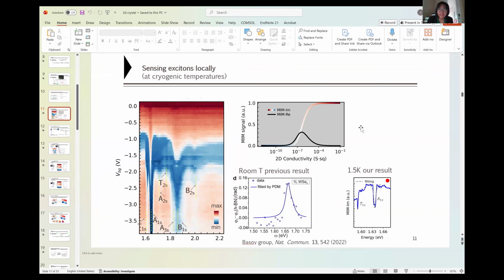Right. So it's a pretty crappy gate, definitely, because the RC constant is very long. In order to use it, we really needed to tune it slowly. We use that as the slow axis because of this. But as long as we can do that, we can get rid of the hysteresis.